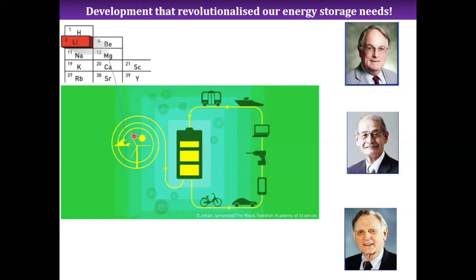Later on they started with sodium and potassium. Now they are going for magnesium and aluminum systems for more than one electron redox reaction. However, starting with this man Whittingham in the 1970s, the TiS2 system. However, there was dendrite formation as charge and discharge continued on the anode part, which led to severe capacity fading, and also led to performance deterioration by heating up the system and later on breakdown.